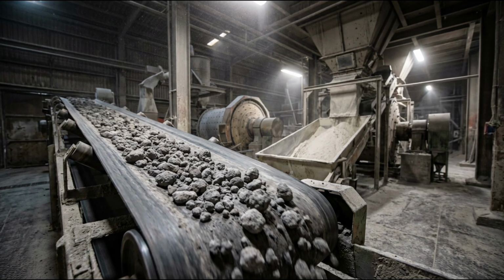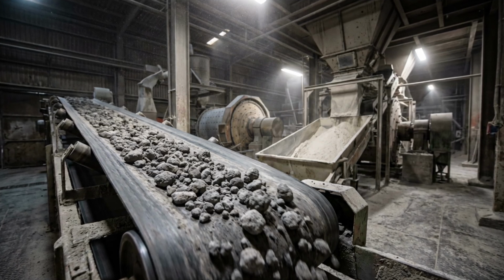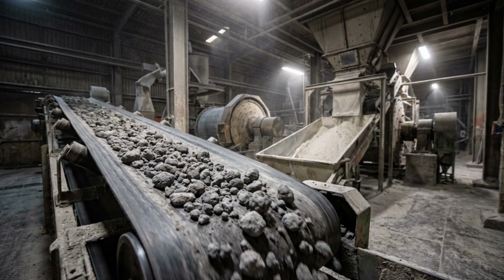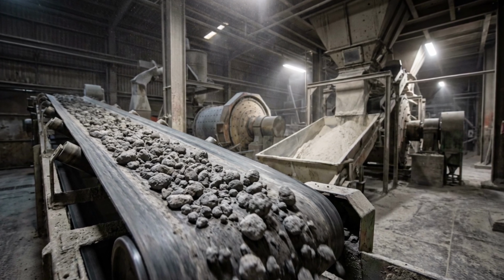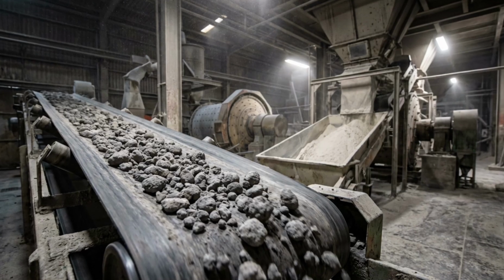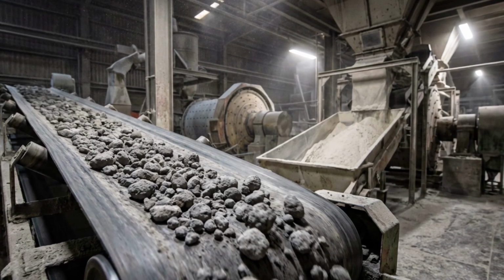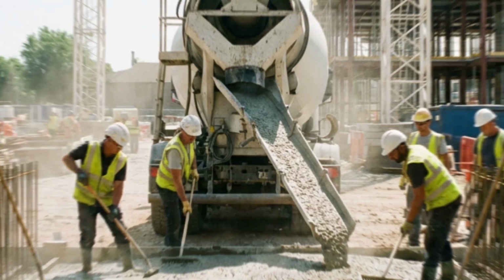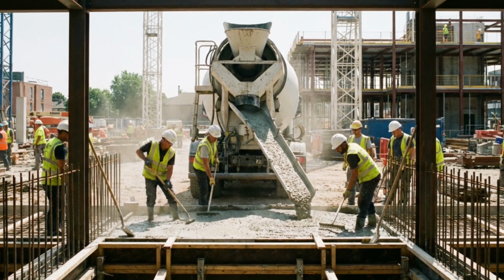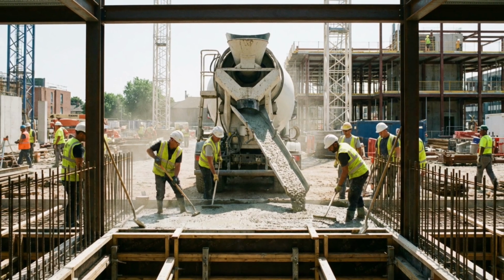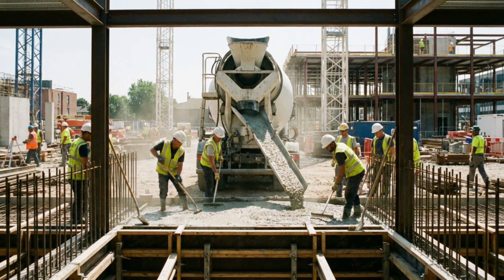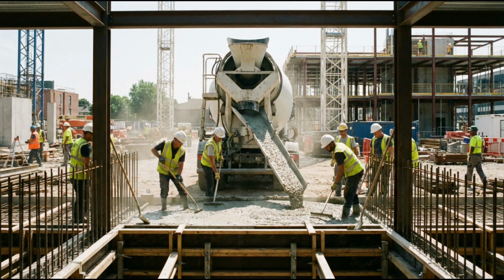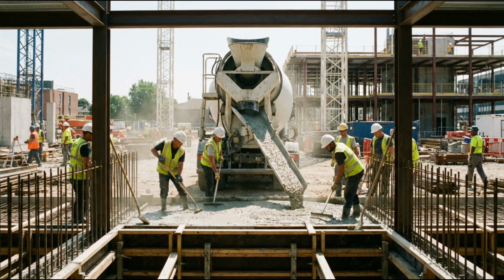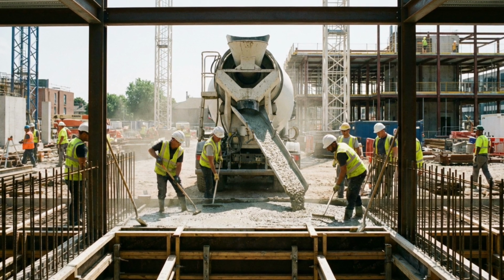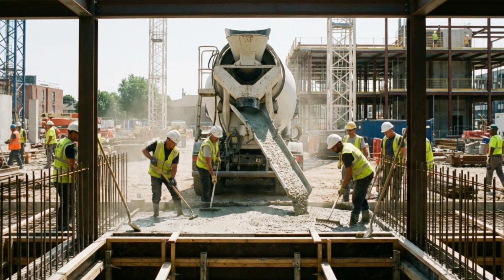Now, can you go further? Carbon capture, utilization, and storage, or CCUS, is the big bet for getting cement below 400 kilograms per ton. Heidelberg Materials is operating pilot CCUS facilities, but this technology is still pre-commercial at scale. Be skeptical of any cement producer claiming near-zero emissions today unless they can show you verified CCUS operational data. The honest answer is that truly near-zero cement is still 5 to 10 years away from mass deployment.